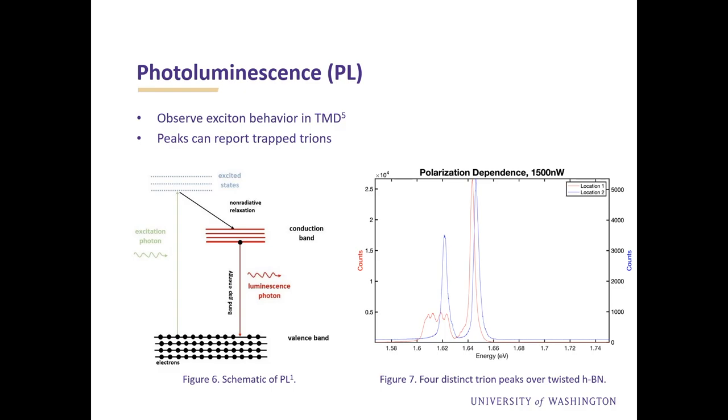While this is an encouraging first result, sample defects, bubbles from the transfer process, or other issues with sample preparation could also explain the trion energy splitting we observe, so it will take further work to be sure of our results.